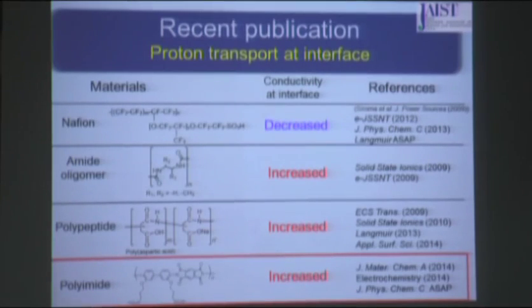Here is a summary of recent publications. For proton transport at interfaces, in the case of Nafion, unfortunately the conductivity decreases, so it is not a suitable material as an ionomer. But we found amide oligomers and polypeptides, which are artificial polypeptides. Today I would like to introduce polyimide. The proton conductivity is highly increased if we focus on the interface.